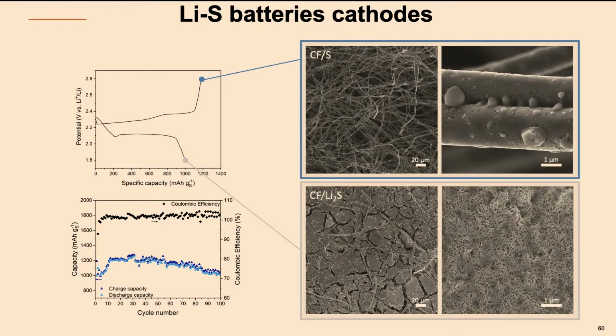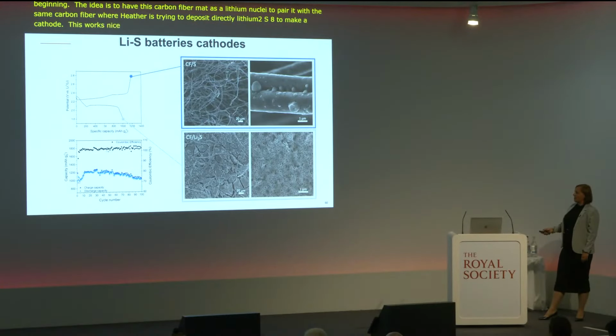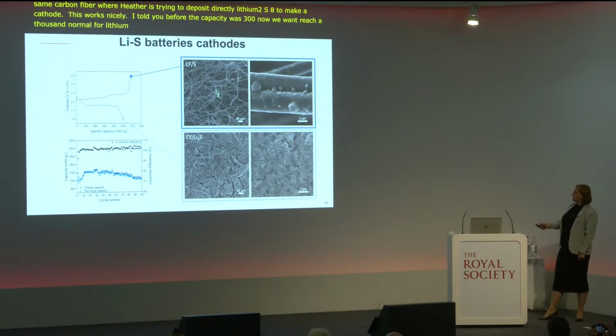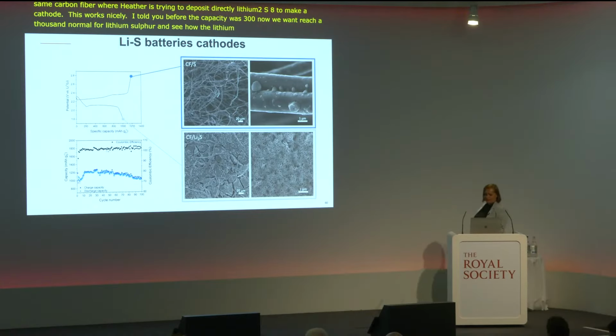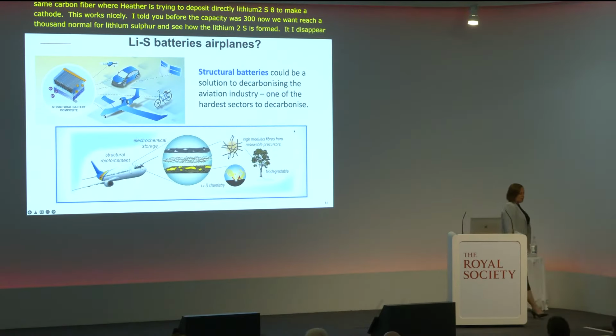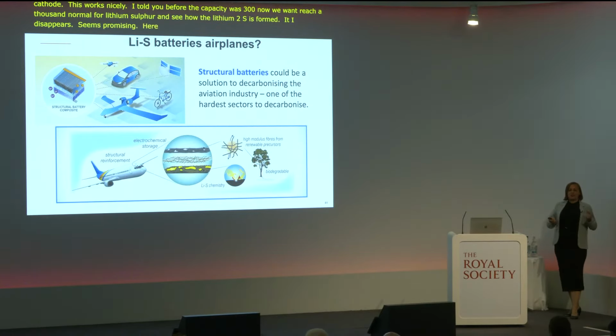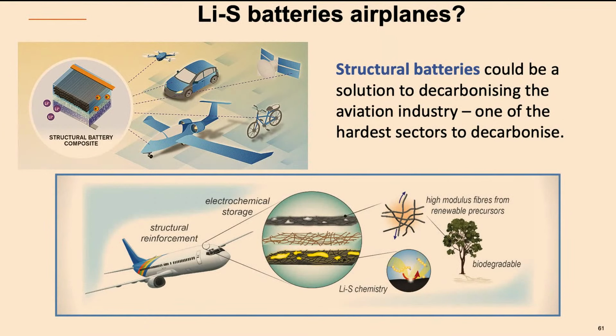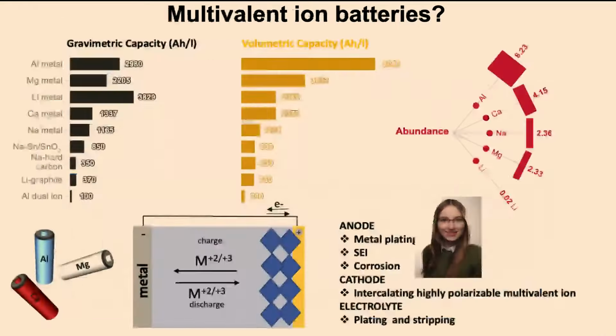Remember that before, for sodium-ion batteries, I told you the capacity was about 300. Now we can reach 1,000 milliamp hour per gram. This is normal for lithium-sulfur. And you could see how this lithium-2S is formed, and then it disappears again. So this seems promising, but again, we're really at the start. But the idea where we're trying to go with this is, can we make a structural battery? Can you imagine one day, since you get a very high energy density, an aeroplane wing made of a lithium-sulfur battery, which is made of these carbon fibers that would be also able to store your electricity. And of course, if these carbon fibers are made from a biomass, it would be even better. But of course, this is a long-term dream, but would be nice.